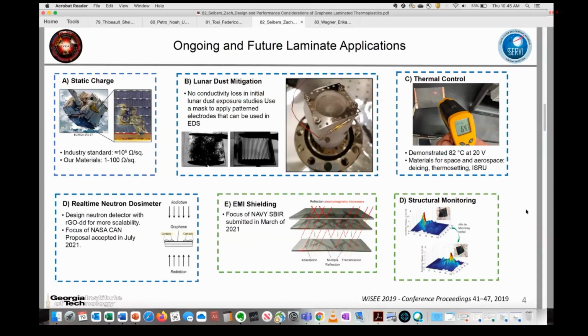what we've turned to in our research is a variety of applications where these laminate layers are promising, and we see a lot of good performance aspects. For example, static charging, we're 10 to the 6, 10 to the 7 times better than we need to be on conductivity or sheet resistance, depending on which way you like to think about it. We are very interested in things like active lunar dust mitigation, thermal control. I think there's some real opportunities for coated plastics to provide really local heating in ISRU type scenarios, or in colder environments where cold thermal issues are a problem. It serves a little bit more purpose. I know usually on the lunar surface it goes the other way. But then of course we've got some other ideas here around neutron dosimetry, EMI shielding, and then of course structural monitoring, which has been mentioned a few times throughout these discussions.